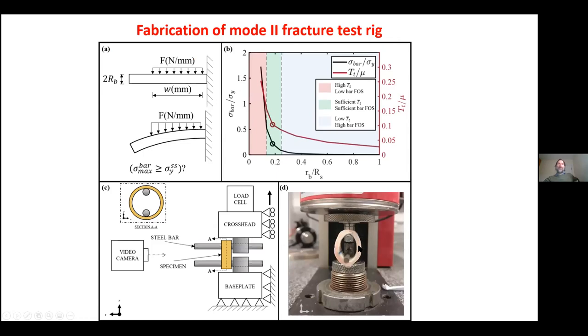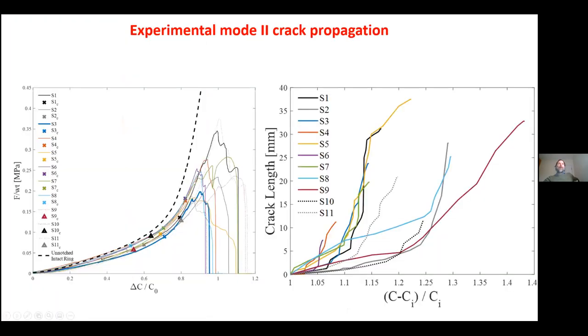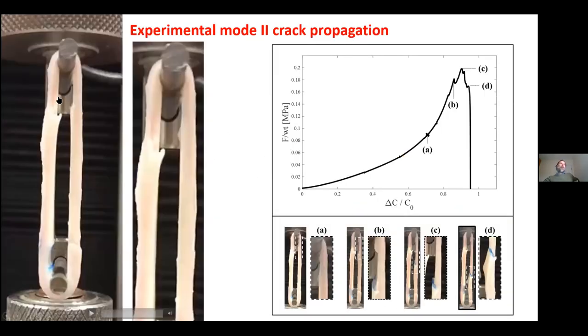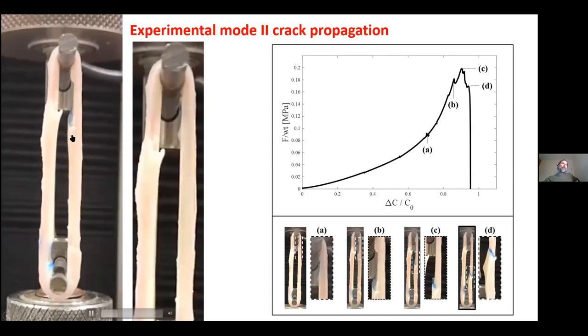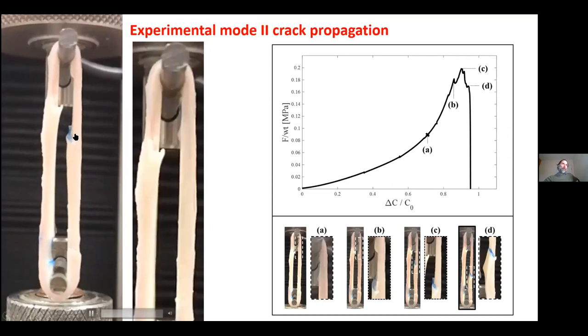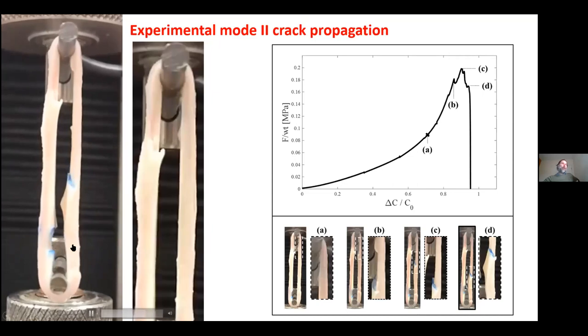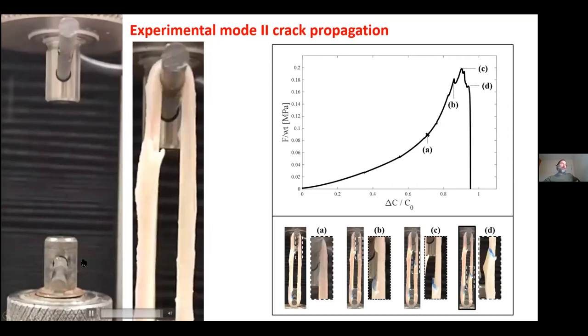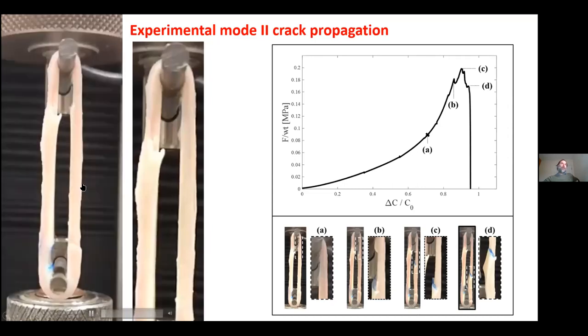This is an artery taken from a sheep. This blue line is where it's marking the crack. Okay, so this is the experimental result. I think this should be a video, I hope. Yes, okay, so you can see the crack is growing along the circumferential direction of the artery. So it's a pure shear crack. You can see it moving along here. In fact, the crack tip is down here. You don't see any normal opening. It's entirely a pure shear crack. And then you finally get a fracture. I'll just play that video one more time.